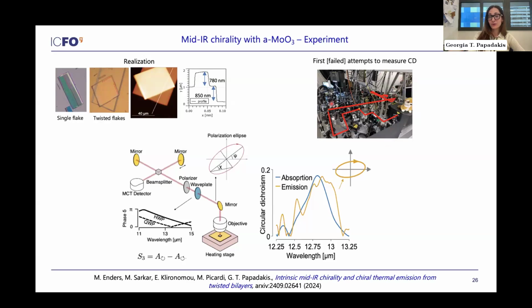So first we tried to do it with a photoelastic modulator in this very complicated experiment that didn't work. And in the end, we did it with our own FTIR by modifying things a little bit. So the most important thing to remember here is that in order to do thermal emission with an FTIR, you basically need to replace the blackbody source of the FTIR with your material sitting on top of a heating stage. So now the source is the material itself, is the sample. These measurements are very difficult because, as you can see, these flakes are actually only 40 micrometers wide. So the thermal emission that comes out of them is very small compared to the thermal emission that comes out of every other component that is in the lab.